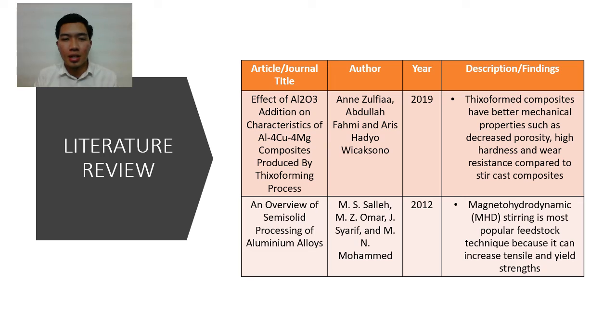After that, the next article that I read is Effect of Al2O3 Addition on Characteristic of Aluminium Copper Magnesium Composite Produced by Thixoforming Process. This article was published in 2019, where the Thixoformed composite has better mechanical properties such as decreased porosity, high hardness, and wear resistance compared to stir cast composites. Lastly, An Overview of Semi-Solid Processing of Aluminium Alloy. This article was published in 2012. Magnetohydrodynamic (MHD) stirring is the most popular feedstock technique because it can increase tensile and yield strength.